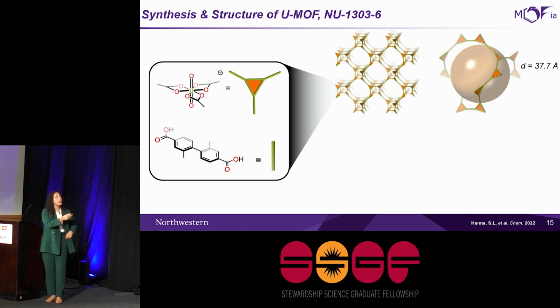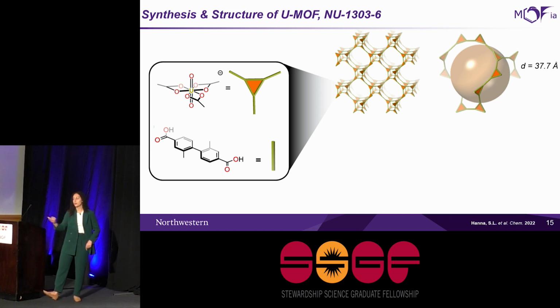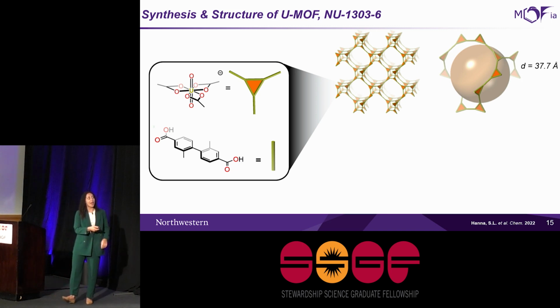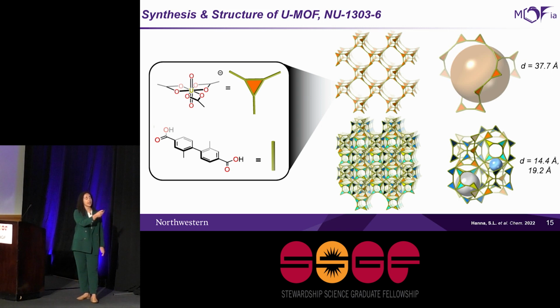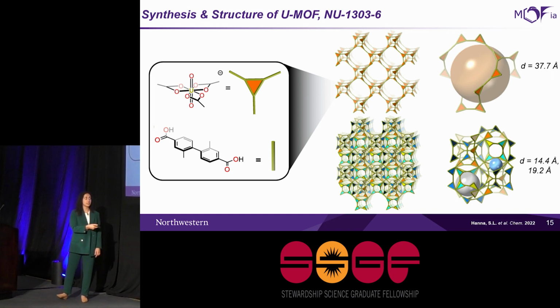So this is a MOF that I named NU13036, and NU is for Northwestern University. We're really fun. We name all of our MOFs after our university. Super original, I know. But you can see the pore size of this MOF, it's a little cut off, but it's almost 40 angstroms. But what I'm showing you here is a very simplified version of this MOF. It's actually 6 of these identical networks entangled together. So in MOF speak, we call this a 6-fold interpenetrated MOF, where the diameter now of the pores within the MOF are about 15 and 20 angstroms.